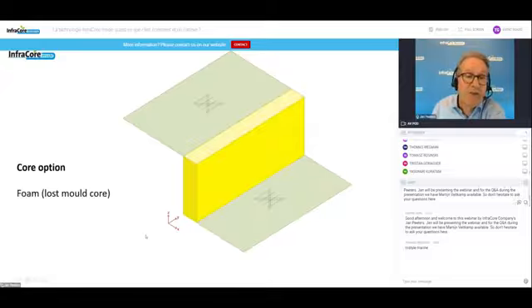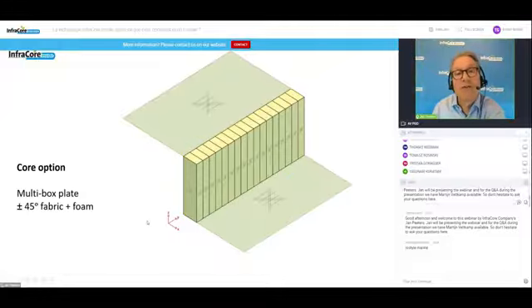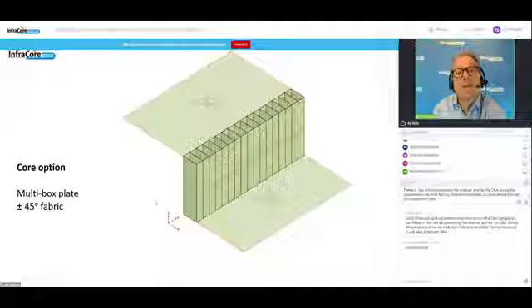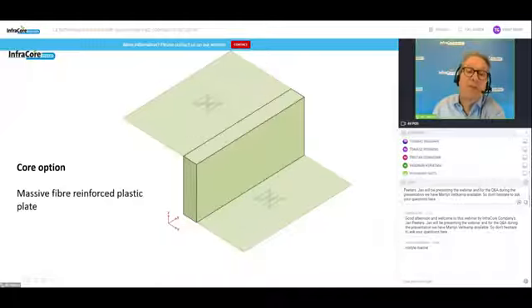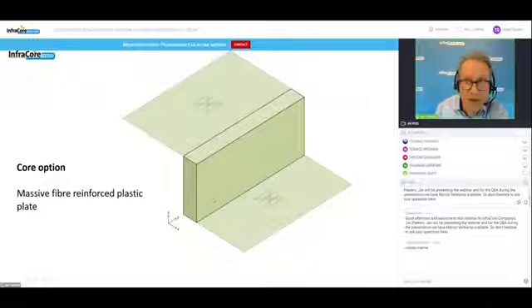Well, there are some options we have. In the core, we could put a foam block. The foam does not have a structural load function. You can add some cross webs in order to improve the shear load in cross direction. And you see some other variants, even the massive blocks. We use these solid blocks of FRP in locations where you have to reduce high local loads, for instance, bolted joints or something like that.